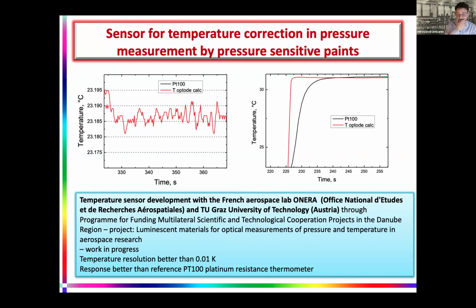On the left side, you can see the real measurements of temperature resolution, or of accuracy and precision, which were made in a big barrel filled with water, highly isolated, so it's supposed to keep the temperature constant, and then you can see this fluctuation. Actually, these two lines represent the resolution of our measurements. So between these oscillations, the precision is 0.01 Kelvin, and even more, the response of this optical sensor compared to standard platinum electric thermometers is almost instant, which is amazing.